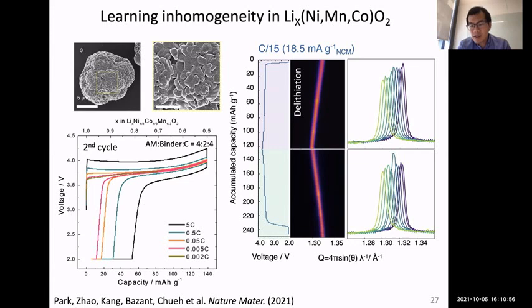We can do a lot of measurements, but either you have time resolution or you have spatial resolution, but you don't have both. And in order for you to learn something about heterogeneity, you need to have time and spatial resolution. This experiment shows you X-ray diffraction. We're taking X-ray beams and recording how the lattice constants of the battery cathodes are changing as you cycle it. I'm not going to get into details here, but these data are very easy to collect. You can have a lab-based machine, or you can go to a synchrotron, and collect in a matter of hours. It's extremely standard, but there's no spatial resolution.